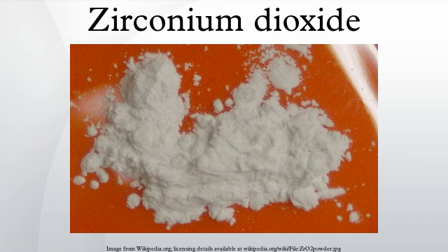Structure: 3 phases are known: monoclinic less than 1170 °C, tetragonal 1170 to 2370 °C, and cubic greater than 2370 °C. The trend is for higher symmetry at higher temperatures, as is usually the case. A few percent of the oxides of calcium or yttrium stabilize the cubic phase. The very rare mineral tazheranite, ZrO2, is cubic.